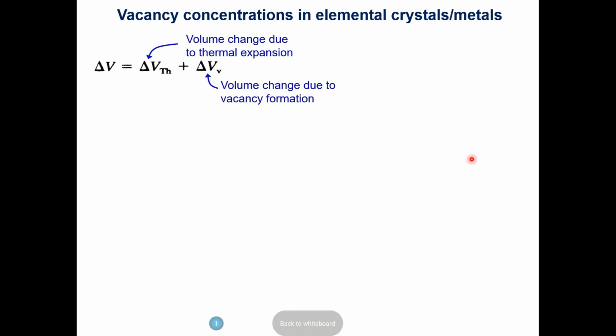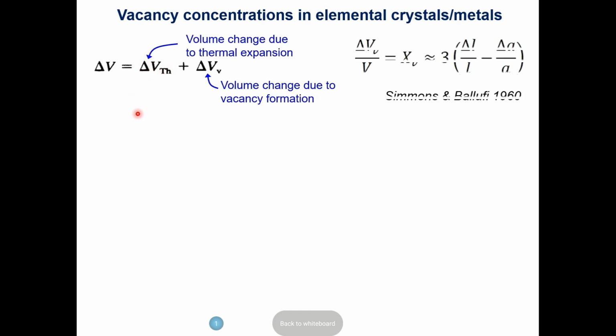So there's another way—before I get there, you can actually look at the change in volume of the system. The total change in volume is given by the change anticipated from thermal expansion: if you heat up the solid, it's going to expand, and you can figure out how much the volume will change because of thermal expansion. There will be an additional volume change due to defects, so you add the defect-related volume change and the thermal-related volume change to get the total volume.